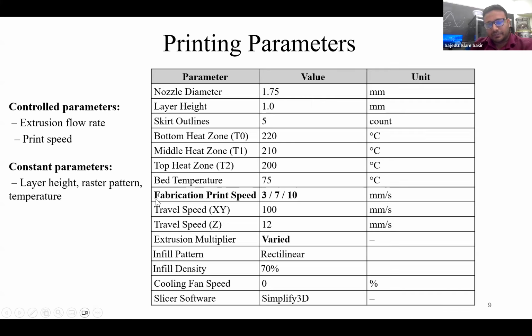And for the fabrication part, we are printing at three print speeds: 3 millimeters per second, 7 and 10 millimeters per second. The travel speed is 100 millimeters per second in the XY direction, and the travel speed in the Z direction is 12 millimeters per second. The extrusion multiplier we can vary, but we are using a multiplier of 1, sometimes 1.2. That's why it's varied. The infill pattern we are using right now is rectilinear, and we also try other infill patterns. The infill density is 70%, and sometimes I also try 80%, 90%, and 100%. And the slicing software we are using is Simplify3D.